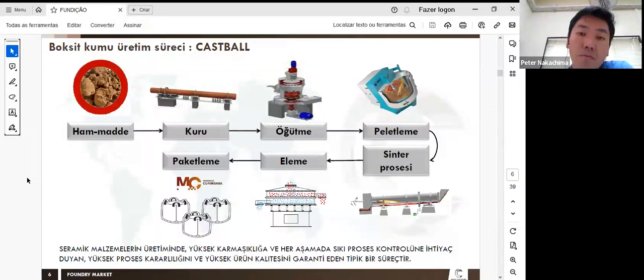The first step after we receive this bauxite here in our plant is to analyze every lot of raw material, and then we prepare the blends of these bauxites to get the right chemical composition of the final product. So for instance, we have to mix different qualities of this bauxite with different amounts of silicon oxide, different amounts of titanium, iron, aluminum oxide, to get to the final composition of the product.